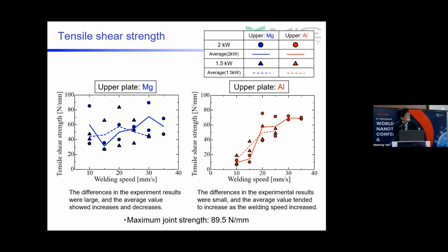When the upper plate was Al, the differences in the experimental results were small, and the average value tended to increase as the welding speed increased. On the other hand, when the upper plate was Mg, the differences in the experimental results were large, and the average value showed increases and decreases. In this experiment, the maximum joint strength was 89.5 Newtons per millimeter.